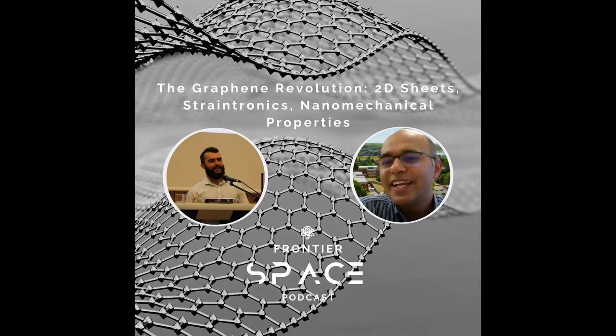There are two things. Either you dope the graphene, like you add some extra material that will sit on graphene and change the chemical or electrical property locally, and then they have a higher affinity toward the foreign molecules which you are going to detect. The other thing is that you introduce defects through laser, make holes, or make structural disorders. They have a different chemical and electrical property, and they can sense differently.